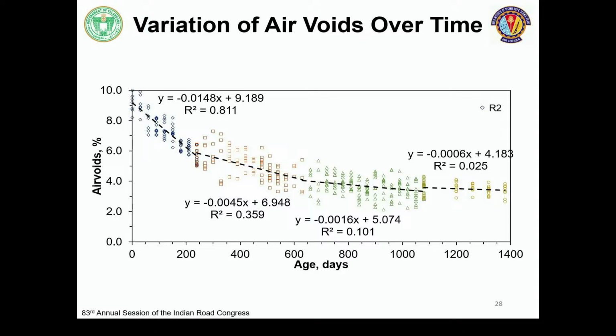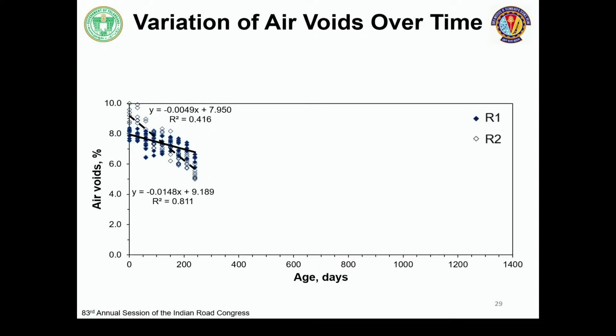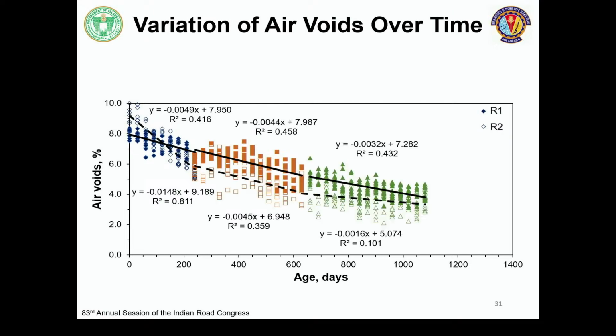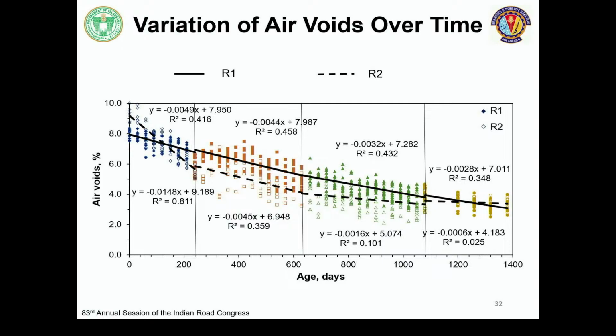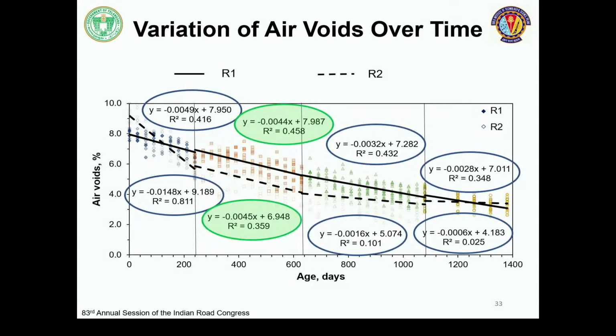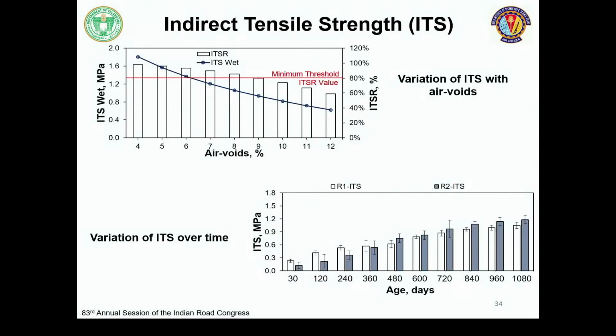What happened in these first initial few days? Because of traffic, there was a secondary compaction. Though the aging was significantly high in the first few days, the rate of aging started reducing because of that reduction in air voids. So I tried to compare the two. We can see that the slope was quite high in the beginning for road 1, and then it started streamlining and almost flattened by the end of the 4th year. We had different equations for that. So initially it was 3 times higher, and then it became almost the same as road 2, and then reduced by half and 1/4. So there is a change in the slope. However, it shows that initial compaction plays a very, very important role.